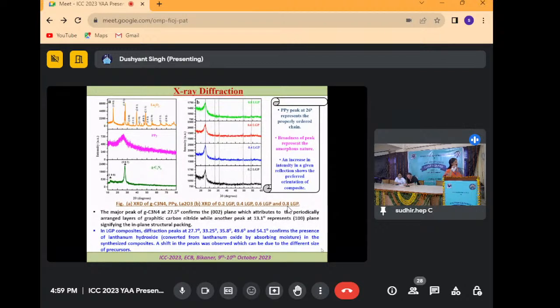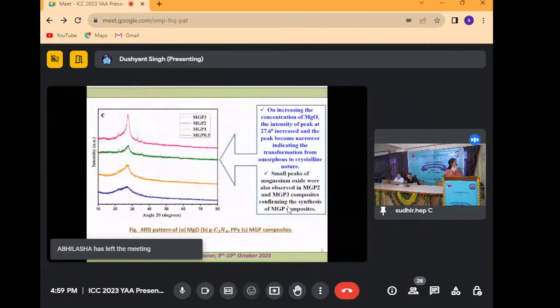by absorbing moisture. And with the graph of the polypyrrole, we can see that the peak at 26 degrees represents the presence of polypyrrole, meaning a properly ordered chain, and the broadness of the peak represents the amorphous nature, and the increase in intensity in a given reflection shows the preferred orientation of the composite. So XRD indicates the composition of LGP, including lanthanum oxide, and this is the X-ray diffraction for the MGP components.